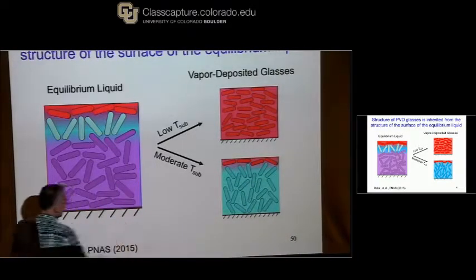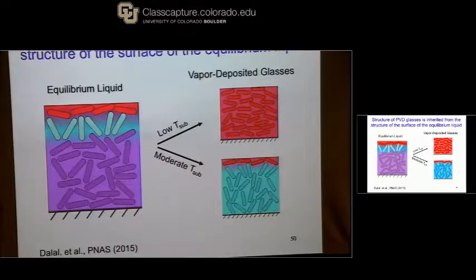So one of the systems that Juan simulated was a film on a substrate of TPD, exactly that molecule I was just showing you. These simulations are done at high temperatures. They're straight molecular dynamics. And what you see, if you look, these are liquids. So if you're away from any interface, these are isotropic materials, okay? But liquids don't have to be isotropic at interfaces. And they're anisotropic both down here at the substrate, which I don't care about, and up here at the free surface, which I do care about.